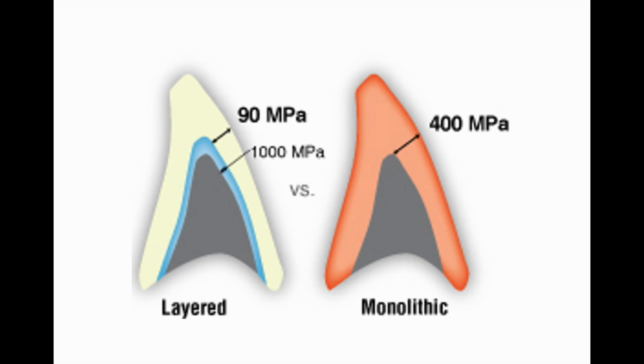The first image shows a layered zirconia restoration where a stronger core having a flexural strength of around 1000 MPa is layered by porcelain having a flexural strength of just 90 MPa. With this, literally the final strength of the restoration gets reduced to around 90 MPa. Usually, the failures occur in these restorations by either delamination or fracture or chipping of the porcelain.